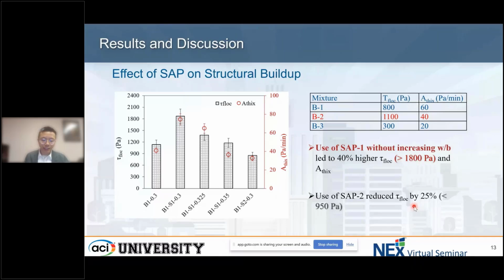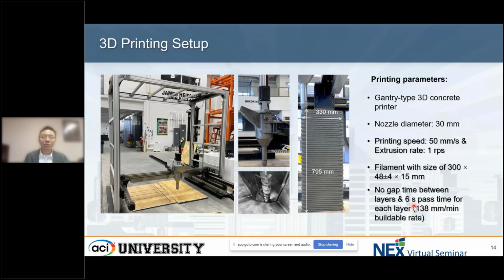And why do we measure these rheological properties and thixotropy? Because these properties are closely related to the printability of concrete. And then I would like to correlate these properties to the actual print quality. So we used a Gantry 3D concrete printer. The nozzle diameter is 30 millimeter. We set the printing speed as 50 millimeter per second. It's pretty fast, and the print filament size is around 48 millimeter in width, and the height is 15 millimeter. And we do not stagger time between layers.